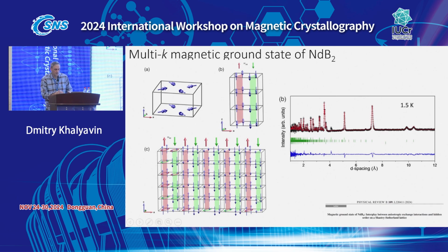So when I understood that stuff, I managed to sort out very quickly this magnetic structure. It's very nice. It's a case where we have alternation of 3 spin up, 2 spin down in respect of the internal field. Our K0 antiferromagnetic component alternates in the crystal, up, down, up, down. And our modulated component does exactly the same.